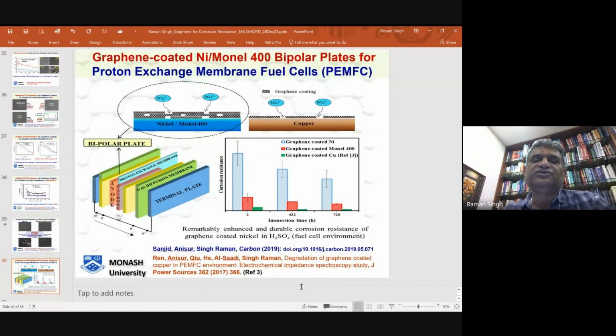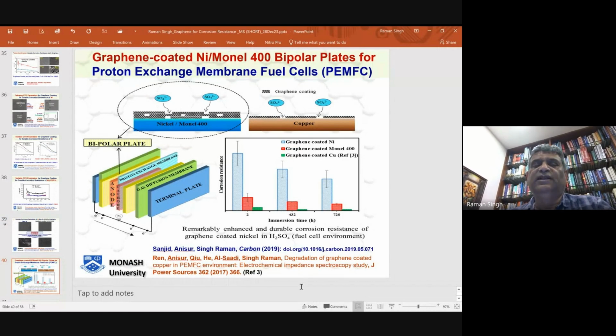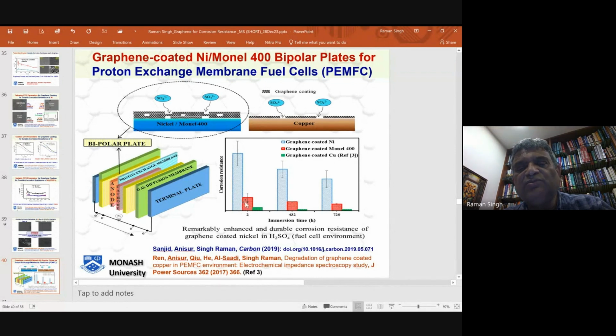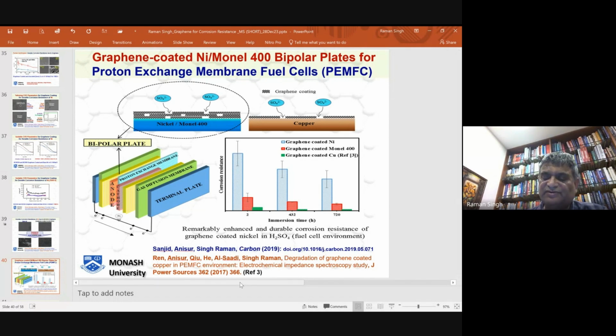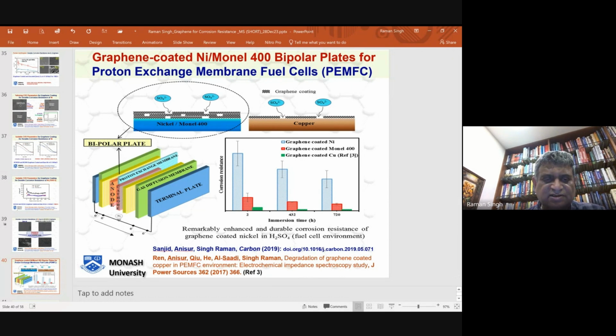Then we started to look into whether we can apply it to real life situations. Earlier we had worked on copper coated with graphene, and we showed that it can be useful for this kind of fuel cell bipolar plates, which I described earlier. And this is the configuration of the bipolar plate. And we showed some improvement. We also worked on graphene coated monel, which is copper nickel alloy. But if you have pure nickel coated with graphene, multi-layer graphene, it showed very good corrosion resistance, and these are all published results in very good quality journals, JPS and Carbon.